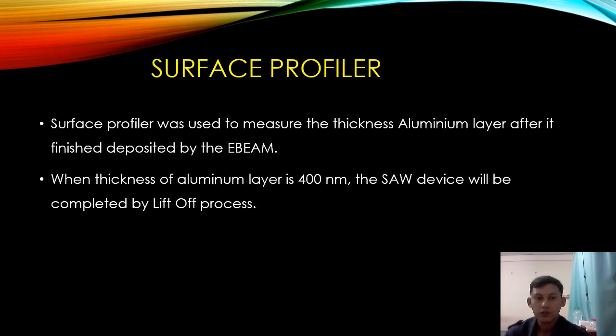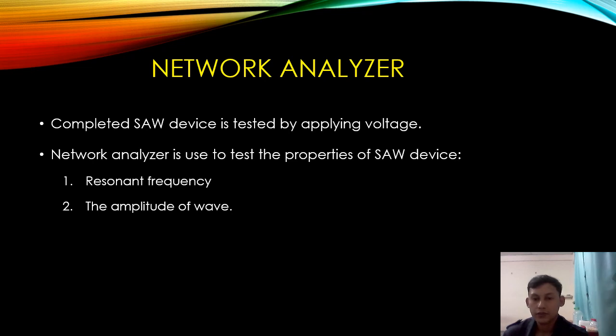Surface profiler was used to measure the thickness of the aluminum layer after it finished deposition by the E-beam. When the thickness of aluminum layer is 400 nanometer, the SAW device will be completed by lift-off process. After the SAW device is complete, it will be tested by applying voltage. Network analyzer is used to test the properties of the SAW device.